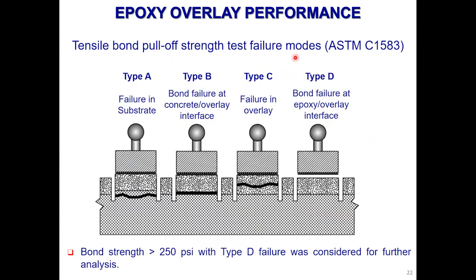For the bond strength evaluation, we use the standard ASTM method C1583. We like to have type A failure. Failure should be in the substrate. But if the substrate strength and the overlay bond strength are greater than 250, it may fail somewhere. Especially this type D, when we have the adhesive between the disc and the overlay, it may fail at the glued surface. In that case, if the strength is greater than 250, even if the failure is D, we take that data because we know the strength of the system is greater than 250.